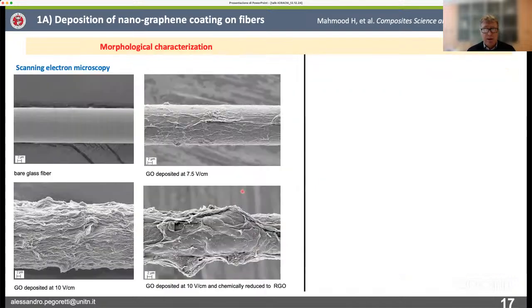The experiment is simple, but the effects are very interesting because you can see here how it is relatively simple to coat the glass fiber by a continuous coating composed by graphene oxide. And here you can see that changing the conditions, for example, the voltage using the electrophoretic deposition, it is possible to change the thickness of the layer deposited. It is also possible to reduce chemically the deposited graphene oxide to reduced graphene oxide, which at this point is a conductive layer, electrically conductive layer.